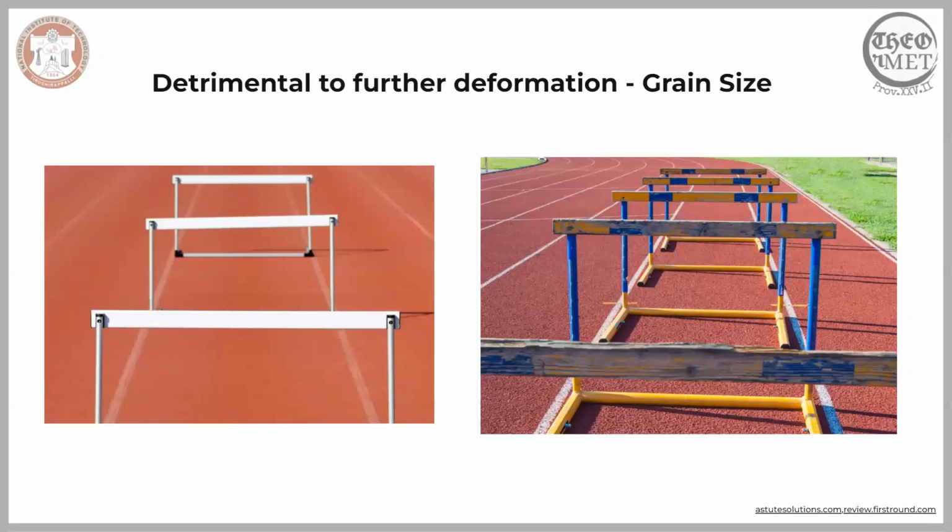So for the first microstructural change, which is the reduction in grain size. As the grain size comes down, we have relatively more grains in the system, hence there will be more grain boundaries. In materials science, the movement of defects called dislocations primarily defines macroscopically the plastic deformation, or simply shape change. So how these dislocations move will determine my shape change. As there are a large number of boundaries, there will be more interruptions for these dislocations while moving, so it will affect further shape change or further deformation.